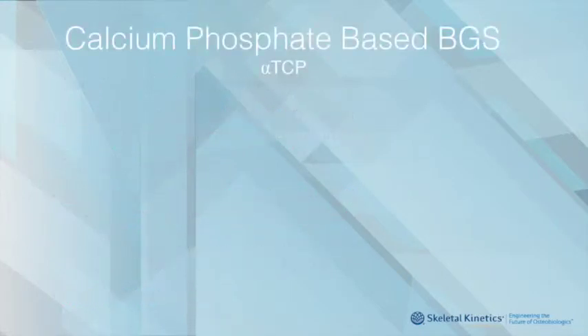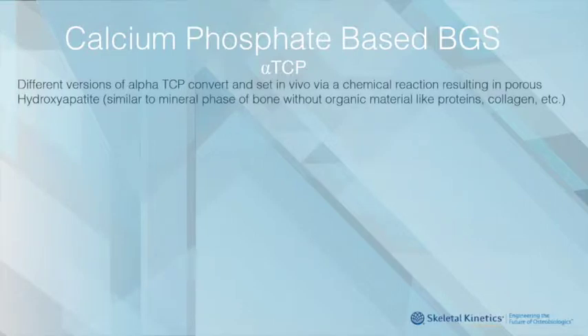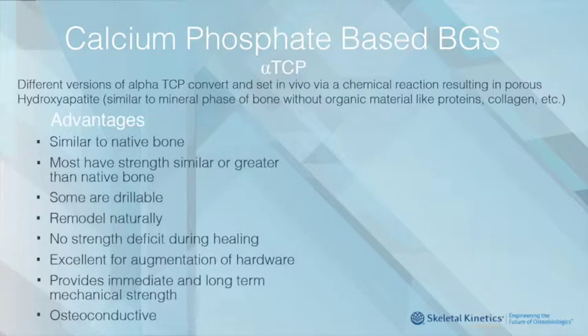First, we'll look at calcium phosphate bone graft substitutes, and in particular, alpha TCP. Alpha TCPs convert and set in vivo via a chemical reaction resulting in a porous hydroxyapatite matrix. Again, this is similar to the mineral phase of bone. The advantage of a graft of this type is its similarity to native bone. Most have strength similar to bone or more. Some are drillable. They remodel naturally. There's no strength deficit during healing. They're excellent for augmentation. They provide immediate and long-term mechanical strength, and by themselves they are osteoconductive.